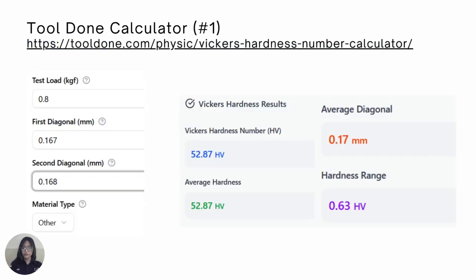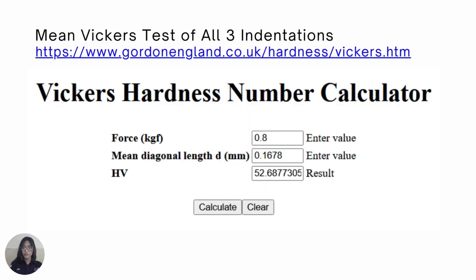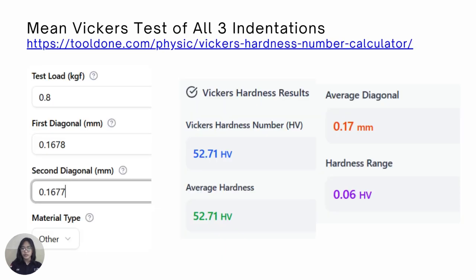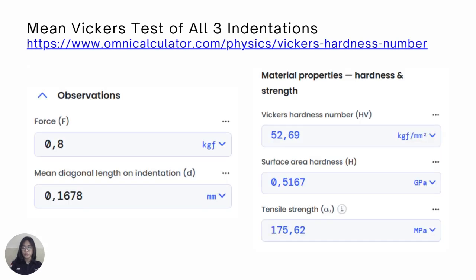Next, we also use Tool Done. So this is the mean Vickers test of all the indentations with the average totaling 52.68 or 52.70. Using Tool Done, we also get the same, 52.71. This one is just different because it shows the average hardness range and the average diagonal. Now this is also for the Omni Calculator, also showing 52.70 when you round it up. This shows the surface hardness and the tensile strength.